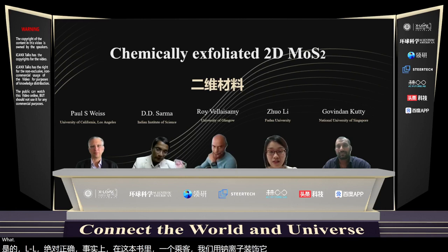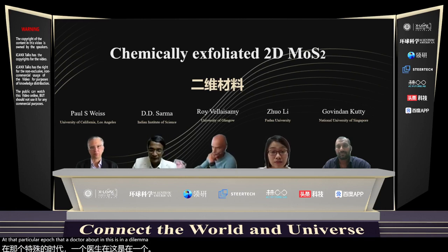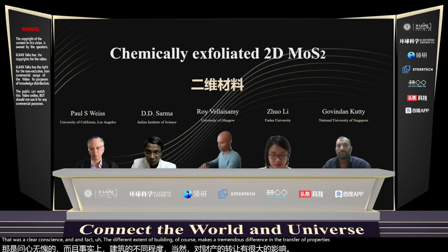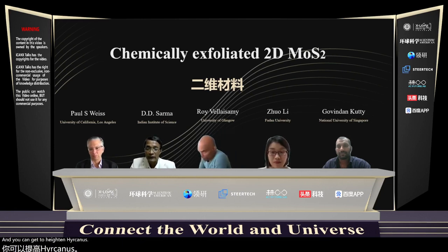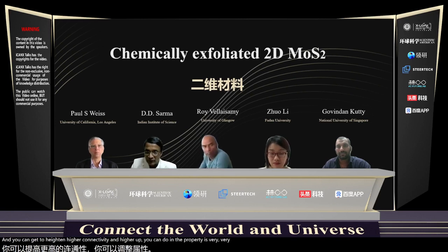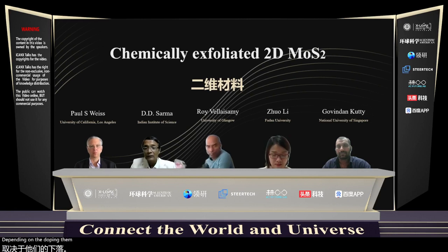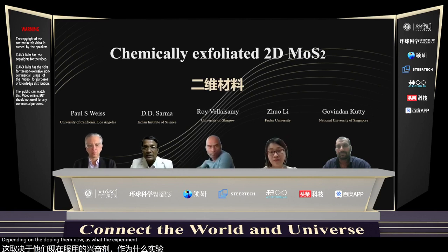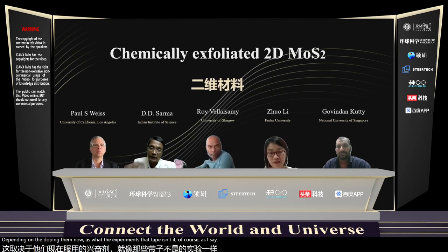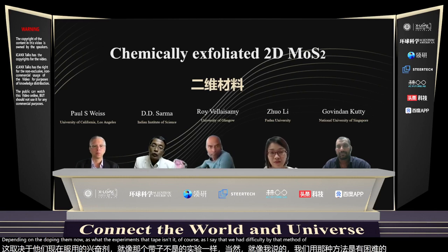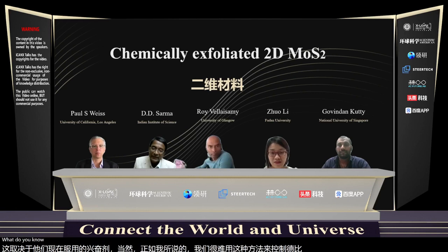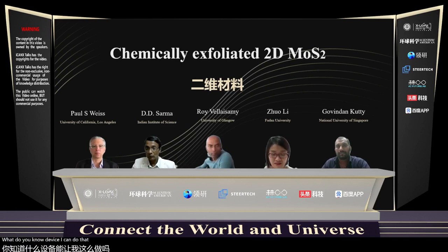That particular paper that I talked about in ACS Energy Letters, that was with sodium ions. And in fact, the different extent of doping, of course, makes a tremendous difference in the transport properties. And you can get to higher and higher conductivity, you can tune the properties very, very significantly depending on the doping level. Now, as for the experiments that I presented, of course, as I said, we had difficulty by that method of controlling the doping. But in a device, I can do that much more easily.